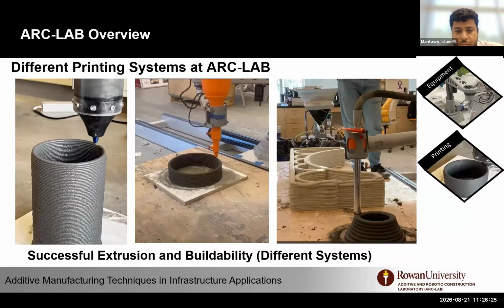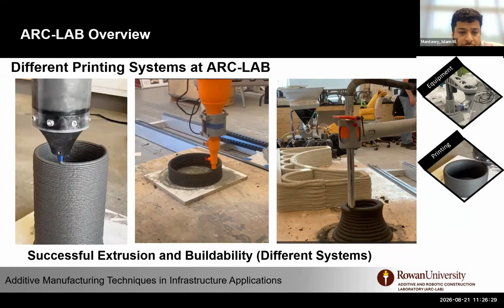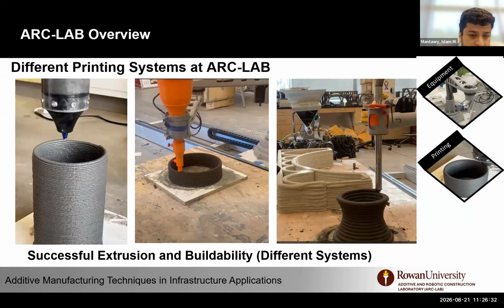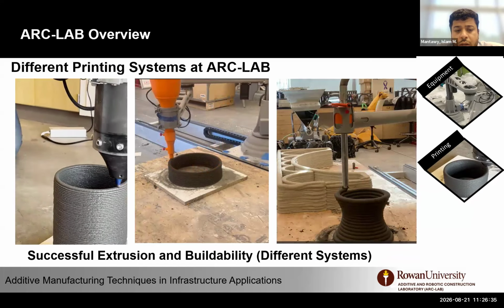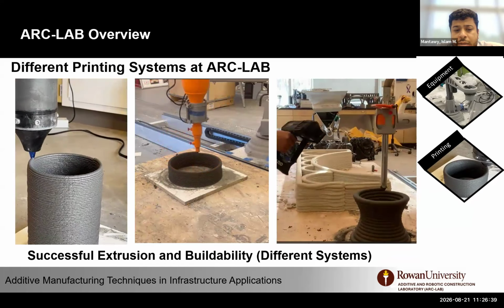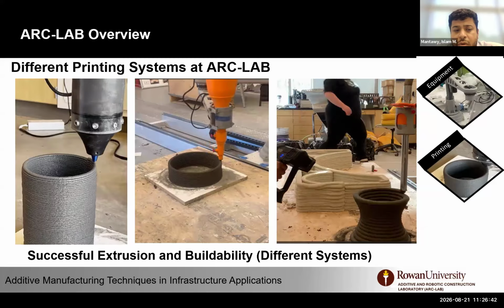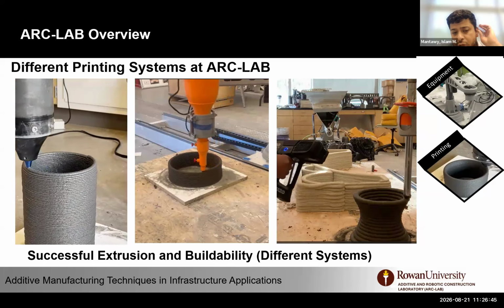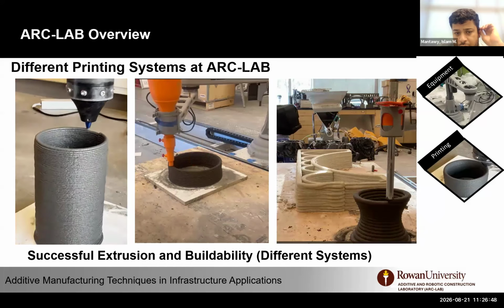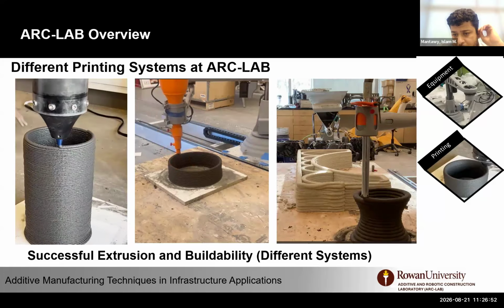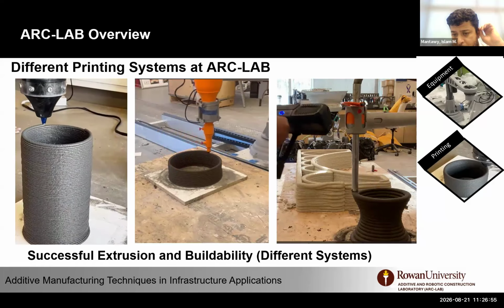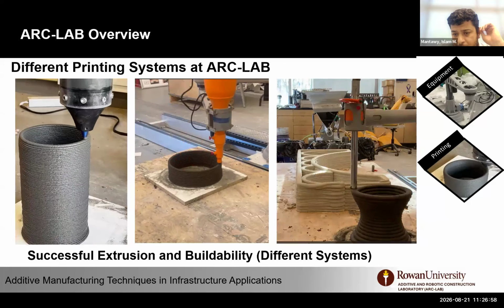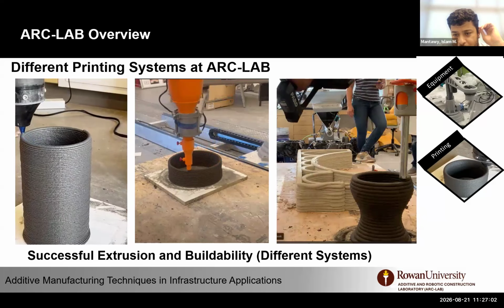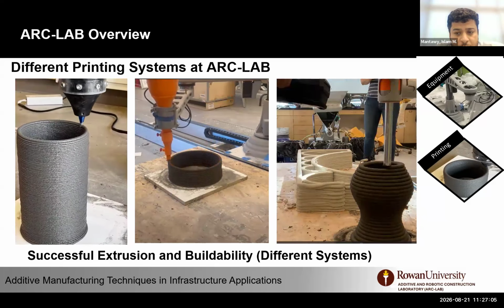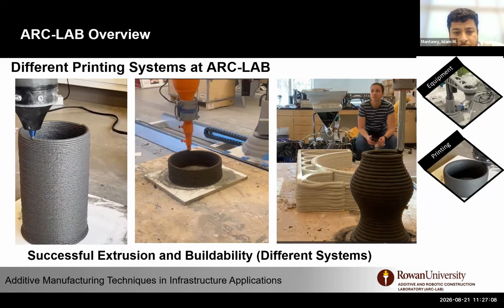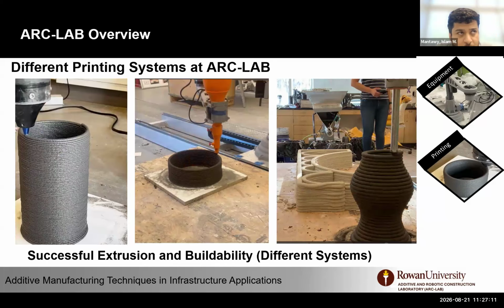So here is a comparison between the systems we have. On the same material that we developed here at Rowan, using locally sourced material, with all the ingredients from 20 miles from the university, you can see the same mix printed with 3 different systems. One is a tube that involves more of a piston type extrusion, the middle one is the auger system printing a much bigger cylinder, and the right side is printing out of the pumping system that we have right to the nozzle. You can also notice someone moving around with a LiDAR to scan the structure as we are building it, to capture the deformations. So the same mix, 3 different systems, passed almost all the printability requirements.